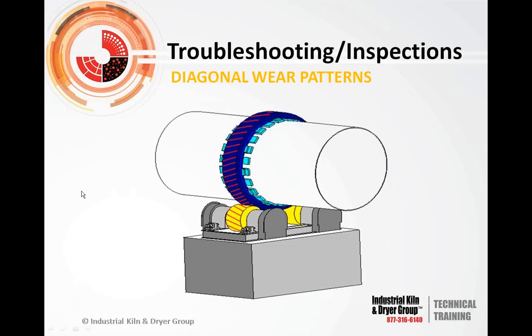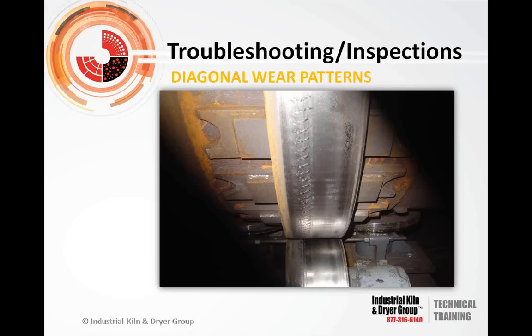Okay, one type of wear that comes up every once in a while, and it's not very common, but you can see it from time to time, is what we call diagonal wear patterns on the faces of the tires and rollers. If you're walking by on your daily inspection and you see these diagonal marks, it's an indication that something has changed with the rollers and how they're thrusting or how they're adjusted, to the extent that it's starting to peel metal. And this is probably the type of wear you'll see out there, and it may not be all the way across the face of the tire, but if you see this band of diagonal marks like this, it's an indication that this roller has been miskewed.